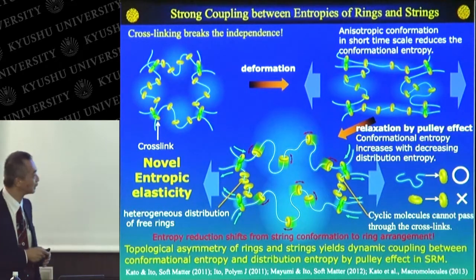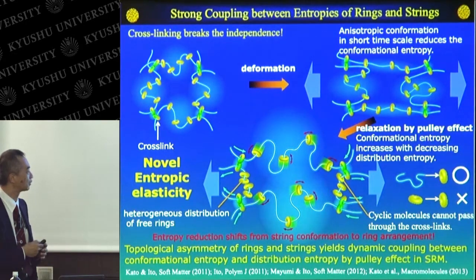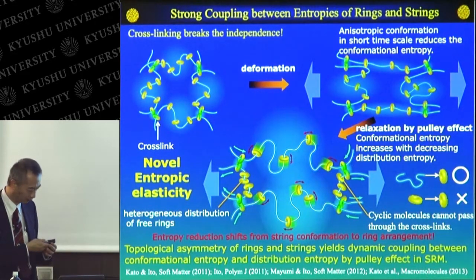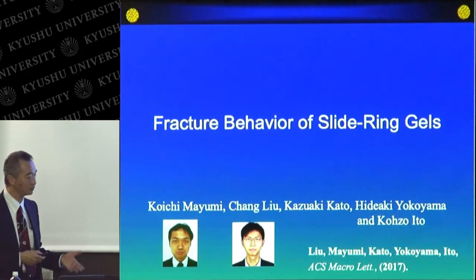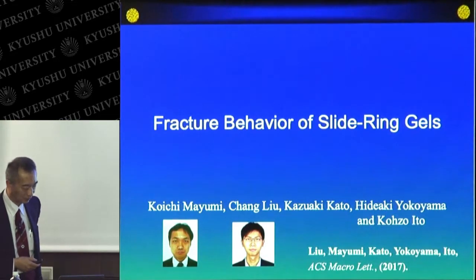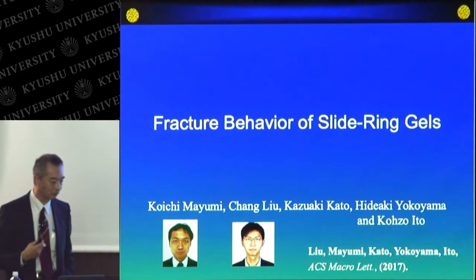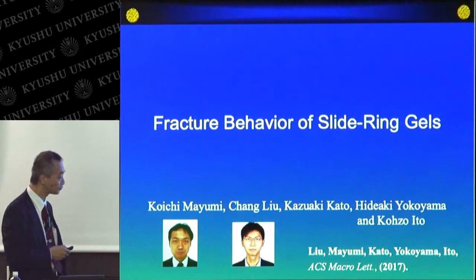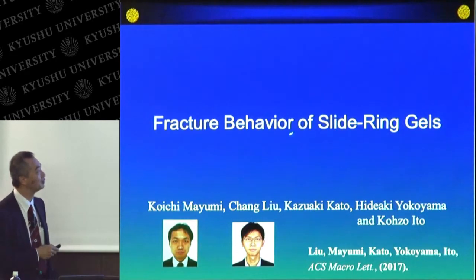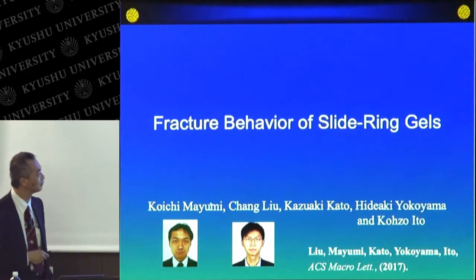This means that the topological asymmetry of rings and strings yields a dynamic coupling between the conformational entropy and the distribution entropy of rings by the pulley effect in the slide-ring materials. And I'd like to show you some recent results of the sliding motion of polymer chains or free rings in the slide-ring materials. I'd like to introduce the fracture behavior of slide-ring materials. This work was performed by Professor Mayumi, Dr. Mayumi, and Mr. Liu in my laboratory.